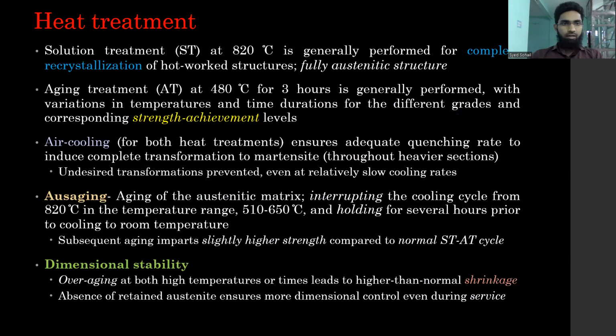Heat treatment, from the heat treatment perspective, as you mentioned, is having a simple heat treatment cycle. Solution treatment is performed at 820 generally for complete recrystallization of hot work structure. So basically, hot work is done, as I mentioned. This has an influence on the microstructure. So now you have to bring back this distorted, work hardened microstructure to fully austenitic, which is soft, and therefore ready for further hard working, cold working, any other form of working that you want to do in the working schedule, I mean the production schedule of the component. So this fully austenitic structure is achieved after solution heating. So that is done.